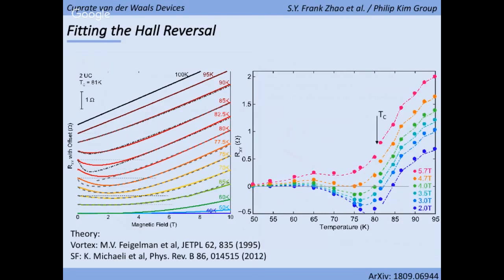So one of the key problems is that we lack quantitative comparisons between theory and experiments. This is where our samples come in. Because our samples are very thin, we can apply the full machinery of superconducting fluctuation theory to these systems. We can very accurately fit the zero field resistance to determine the temperature at which Cooper pairs become energetically favorable. Next, we can fit our curves above and below that temperature with the superconducting fluctuation theory as well as one particular vortex theory.